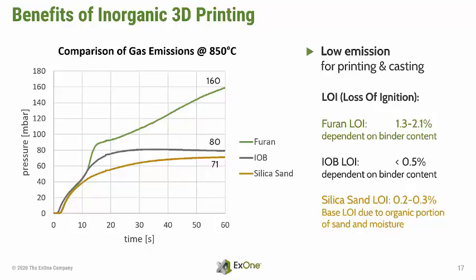The major advantage of using a low-emission inorganic binder for the 3D printing of sand cores is the improved air quality in the foundry and the improved yield of the castings because much fewer exhaust gases are generated. Core vents that remove trapped gas during casting are no longer needed because no such gas is created. There is almost no organic content in the binder to burn or vent. This will help to avoid gas bubbles in the casting and is therefore leading to higher yield, as I mentioned.